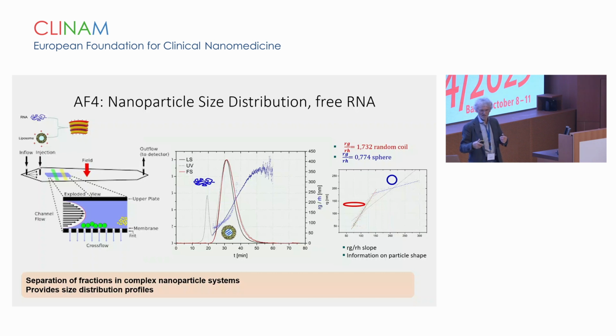And here you see results from a lipoplex formulation. You see these 2 peaks, a small one, this is free RNA. You see a big one, this is the lipoplexes or the lipid nanoparticles. And you get lots of information on that, like the size by different methods at each individual elution time, the RG to RH ratio, which gives you shape information and so on. So that's already very good.